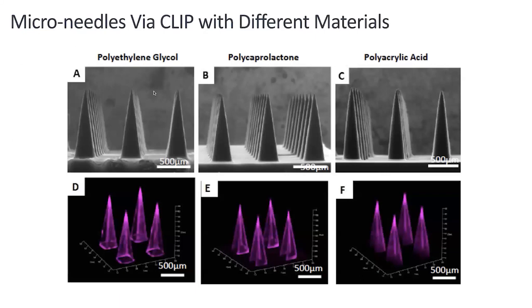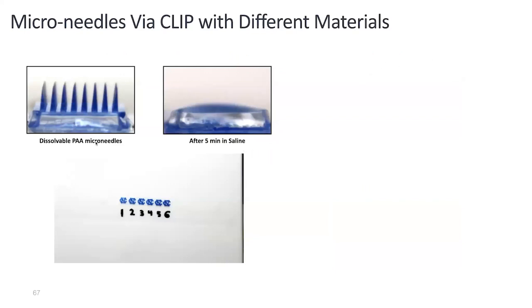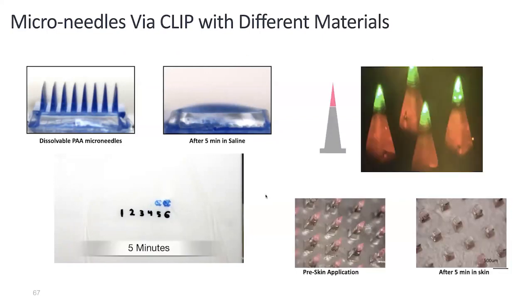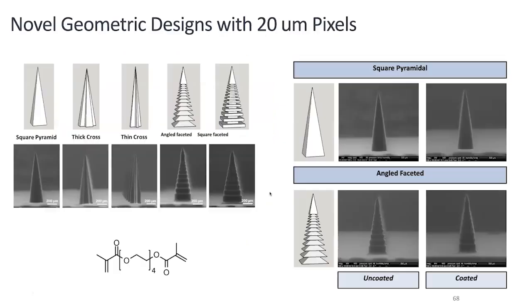You can make them out of a wide range of chemistry: hydrogels, cross-linked hydrogels, biodegradable systems, even water-soluble systems. Here's an example of polyacrylic acid microneedles that we printed. We did it with different formulations so that we control the molecular weight, and we're basically controlling the dissolution kinetics. I thought I'd show the North Carolina logo for Heather here. It's reminiscent of when she was an East Coaster. But the point is different dissolution rates for controlling pharmacokinetics and getting into controlled delivery systems.